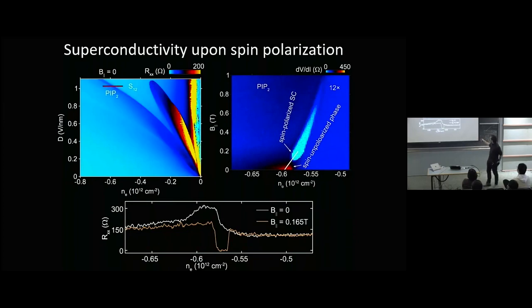Actually, we have other data. The reason it stops superconducting here is actually because there's a very slight misalignment between the magnet and the plane of the sample. If you do this more carefully, you find it goes as high as we've had magnets go, so at least 30 times the Pauli limit. And it seems like the ground state is just spin polarized. So these are funny superconductors because they have pretty large coherence lengths. So 1 or 2 millitesla sometimes will kill them out of plane, but a Tesla in plane won't kill them. So there's an anisotropy factor of at least 1,000.